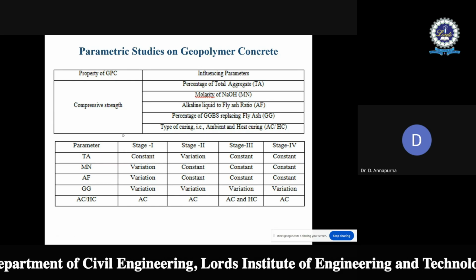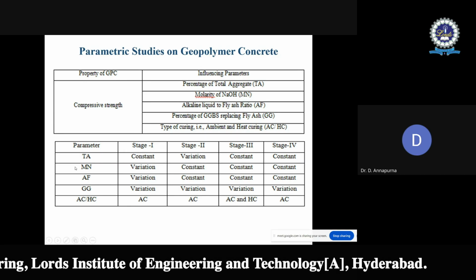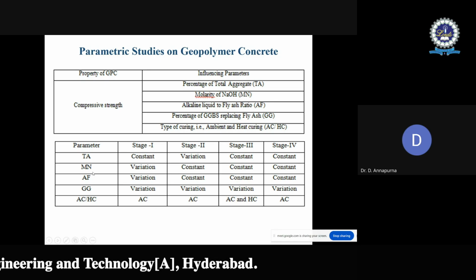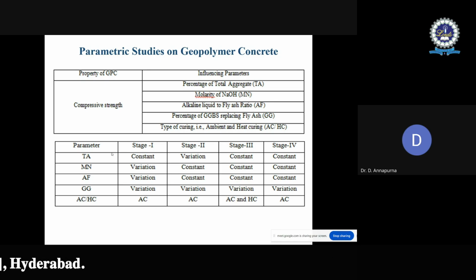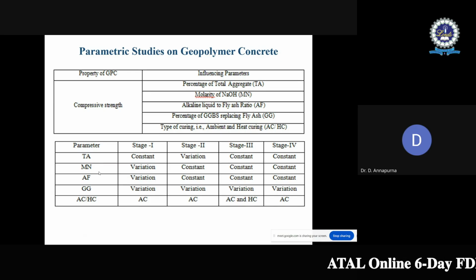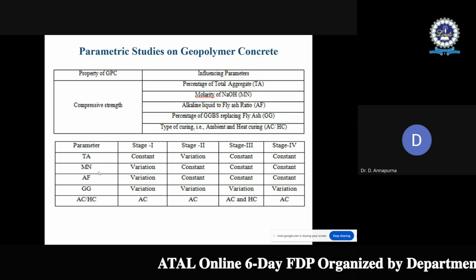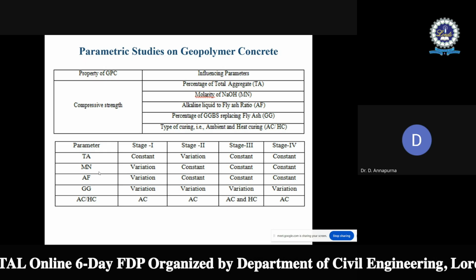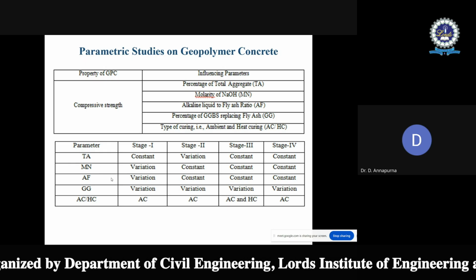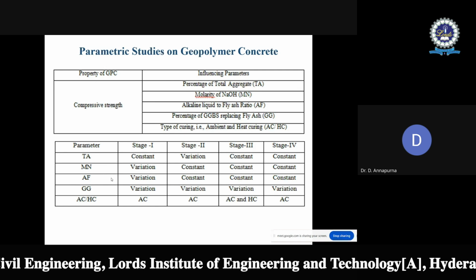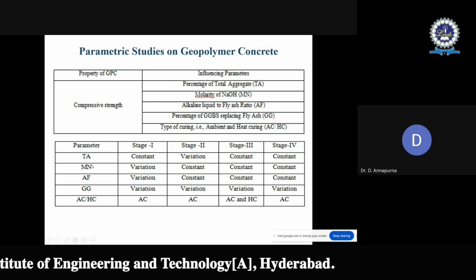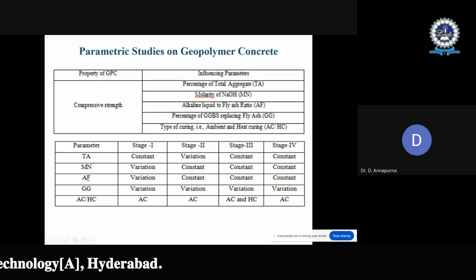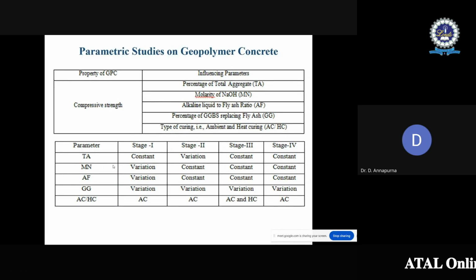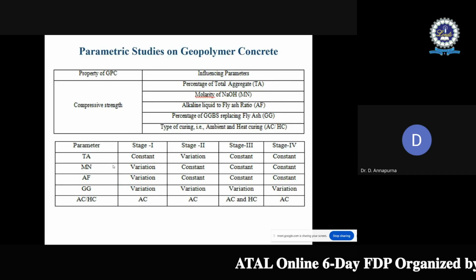Then, as per the literature, it is identified that as the molarity of NaOH increases, geopolymer concrete strength increases. And most of the researchers have done the research with molarity between 8 to 16. So that is the reason in this particular work also, the molarity of NaOH is considered as 8, 12, 16. So 3 variations are taken. Then comes the alkaline liquid to binder ratio. Here the binder is fly ash and GGBS. So that ratio is considered as 0.3, 0.5, 0.7.